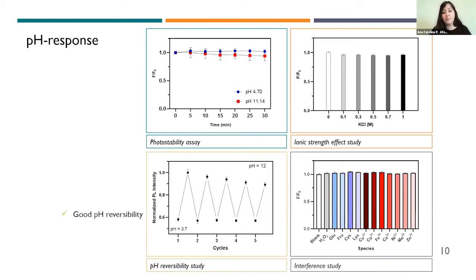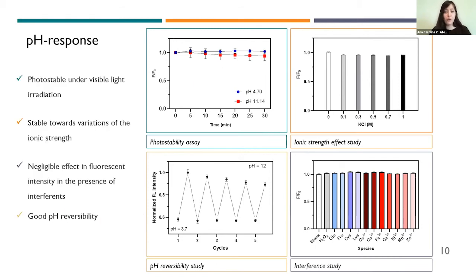And finally, the pH reversibility of the fluorescence emission of the carbon dot was tested by adding the carbon dot to a buffer solution of 3.7 and repeatedly switching the pH between 3.7 and 12. There was a reproducible reversibility of the carbon dot's fluorescence signal with pH variations, despite a slight decrease in the fluorescence intensity at basic pH. Overall, the carbon dot coated with fluorescein showed itself to be highly stable.